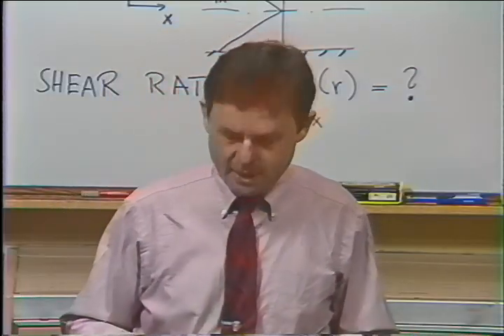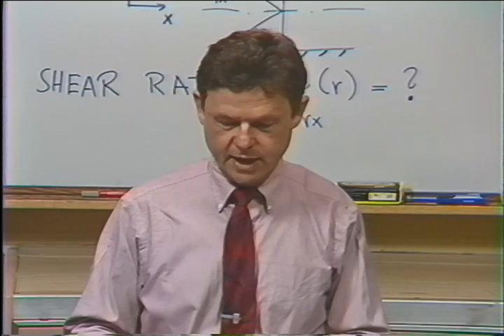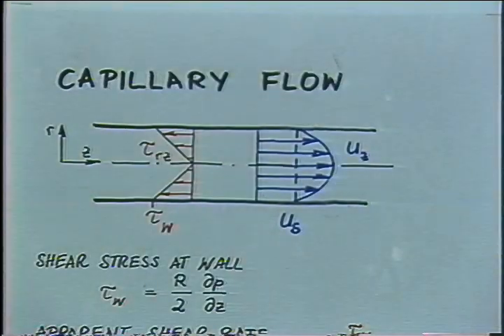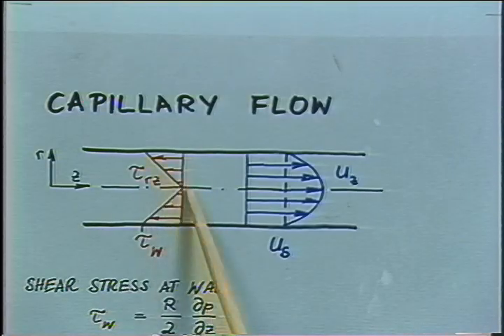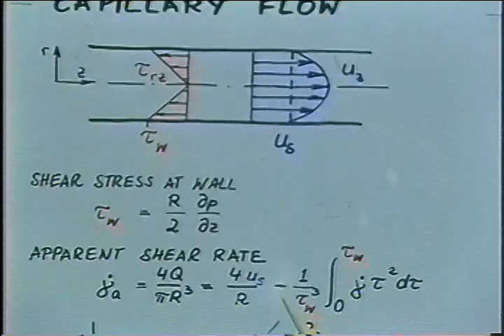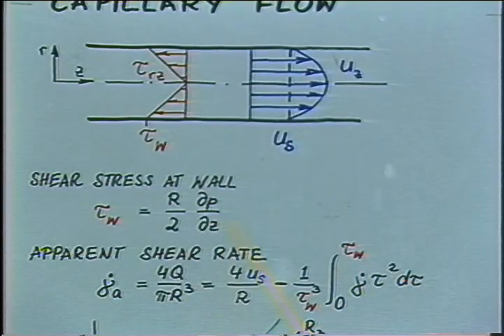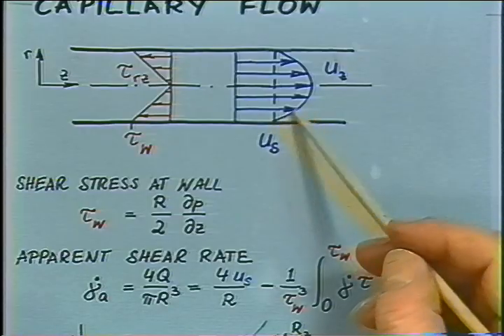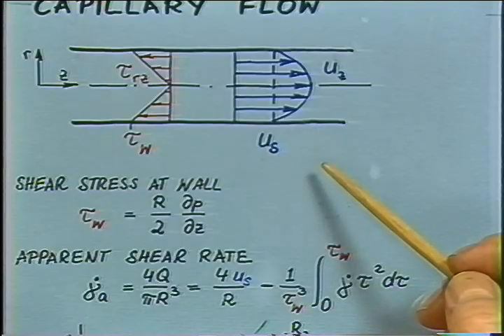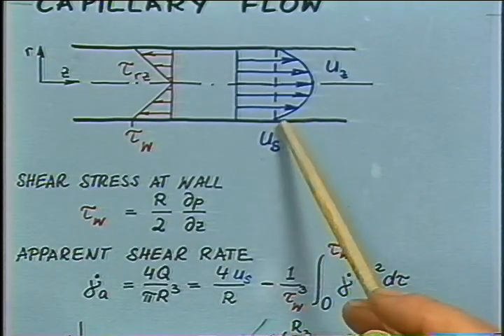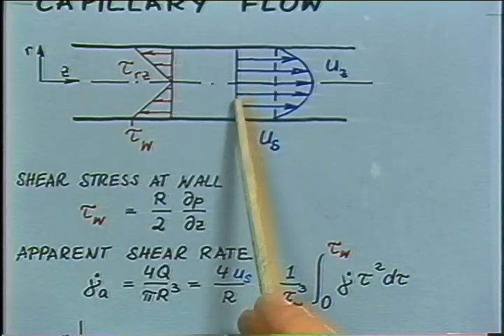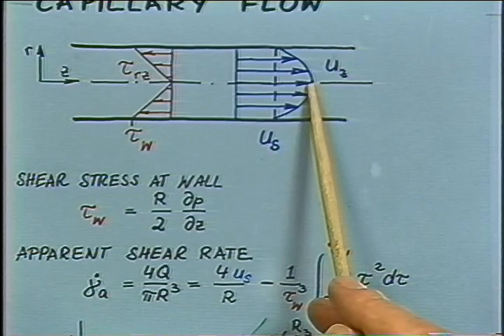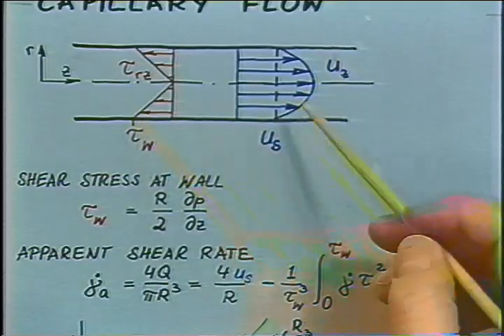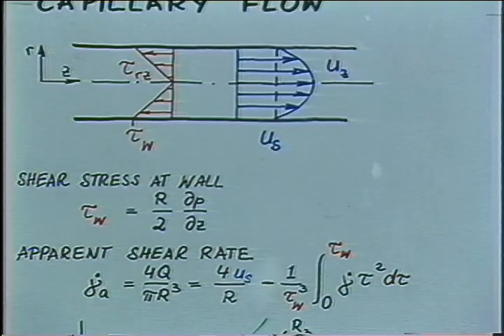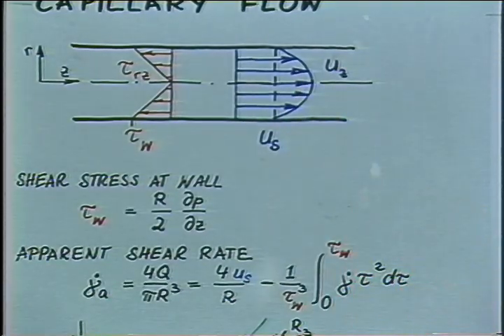Another interesting phenomenon to discuss is slipping at the wall of the capillary. The shear stress distribution is not affected by slipping at the wall. We still would have the linear relation for the shear stress as calculated from the measured pressure gradient in the capillary. However, the shear rate at the wall is somehow hard to determine, because our measurement is not giving us the shear rate, it gives us the volume flow rate. And you see the volume flow rate has a slip contribution and a bulk contribution. And there's a deformation. The material doesn't move through this capillary like a plug. There's a finite shear stress at the wall, and due to that shear stress, there's a bulk deformation, which gives rise to some velocity gradients and gives rise to a contribution in this experiment.